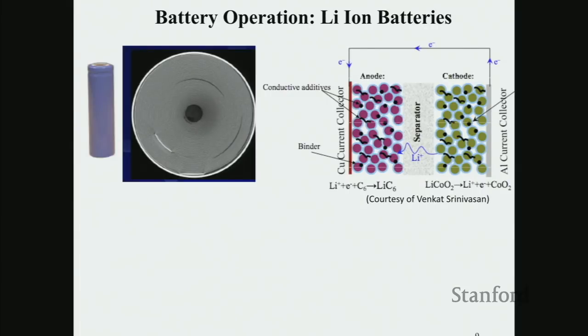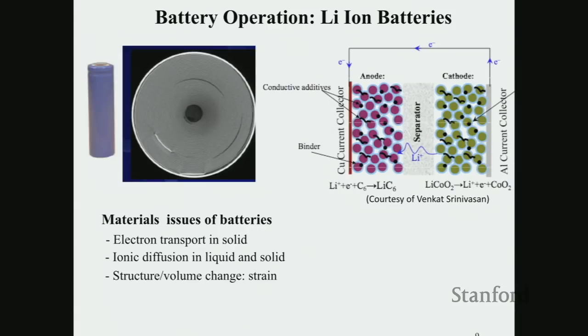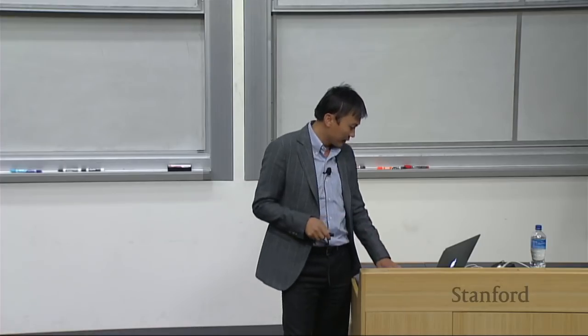Once you charge your battery, lithium goes to the anode. Electrons also come to the anode. They meet in the anode, that's in the charge state. And in the discharge state, they go back to the cathode, back and forth. Whether a battery can work or not, you need to deal with these issues. This determines a lot about how the batteries work, whether it's safe, how long you can use it for. And you need to move electrons. If you want to charge your battery fast, you better move your electrons fast. Ion diffusion also involves ions squeezing into the crystal structure, in and out. There will be strain associated with the crystal structure because there will be volume expansion taking place.